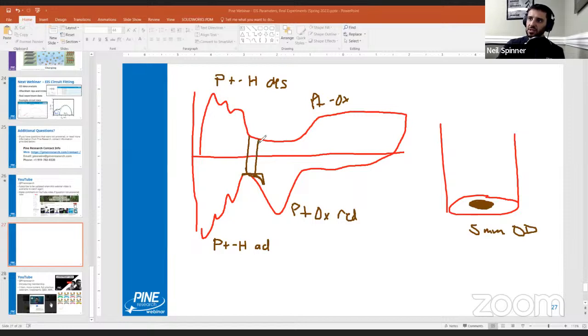So what it allows you to do is subtract this capacitance, this current, because it's just double layer capacitance. And so what you're left with is that, technically, or at least theoretically, the surface area of this current data is related just to the platinum hydrogen adsorption desorption process. So what you can do is integrate it, you get the surface area.